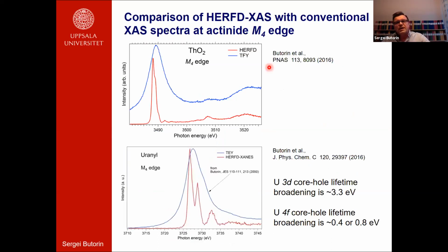And indeed, the slide shows a comparison of the HERFD spectra with conventional XAS spectra at actinide M4 edge for thorium dioxide and uranyl nitrate. You can see a dramatic improvement in resolution here. We are able to resolve additional structures, even small satellites, instead of a single line for thorium dioxide. And instead of a hint of a shoulder for uranyl nitrate, we resolve about 4 different structures.